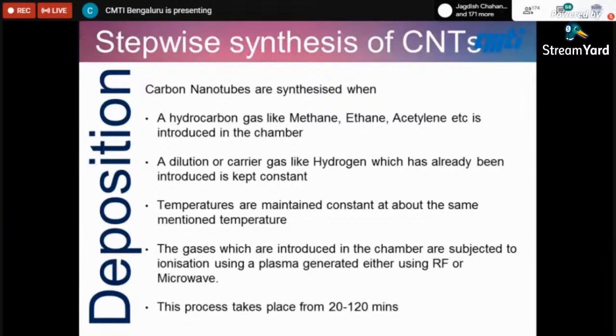And here comes deposition. Once you have nucleated, the same process is run. You already have hydrogen inside. You add methane, ethane, or acetylene into the chamber. The temperature is more or less maintained constant. Then you again ionize it using plasma, using either an RF or microwave generator, and allow the process to happen for 20 to 120 minutes. And then you will find that you have started synthesizing CNTs.